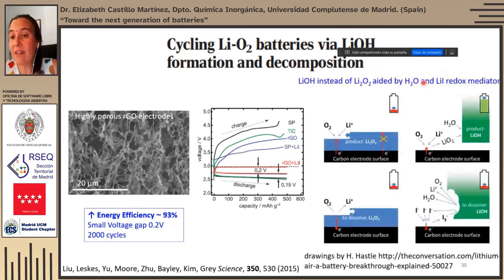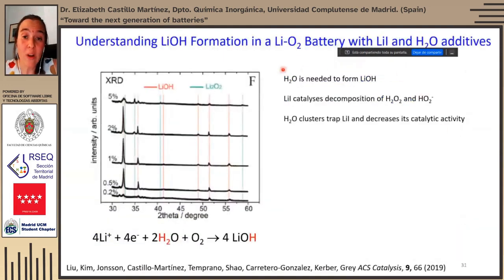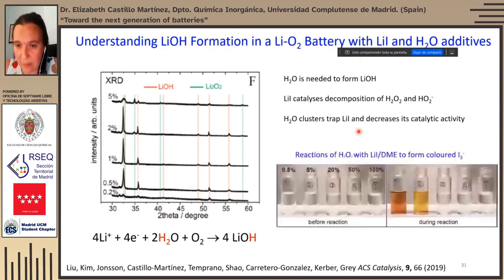And the presence of the lithium iodide redox mediator helps on decomposing as well the lithium hydroxide product as would be for the lithium peroxide. Interestingly, water is needed to form lithium hydroxide, but the lithium iodide is also needed to form lithium hydroxide, because lithium iodide catalyzes the decomposition of the peroxide species. And in the absence of lithium iodide, it is lithium peroxide that forms. However, if there is lots of water, the water cluster traps the lithium iodide, and then it decreases its catalytic activity. So there is an optimum water content that can be put into the electrolyte to have the desired lithium hydroxide reactivity with proper reversibility.